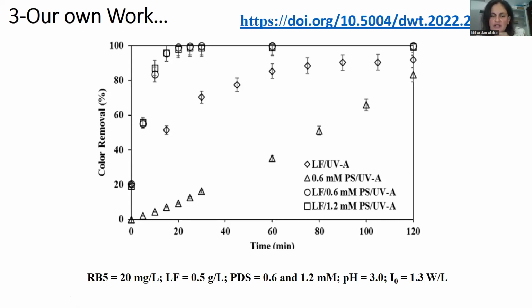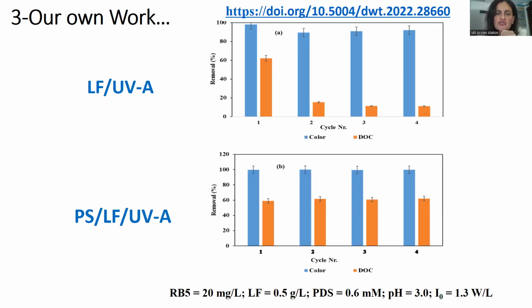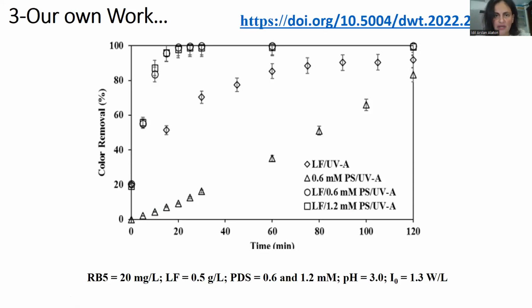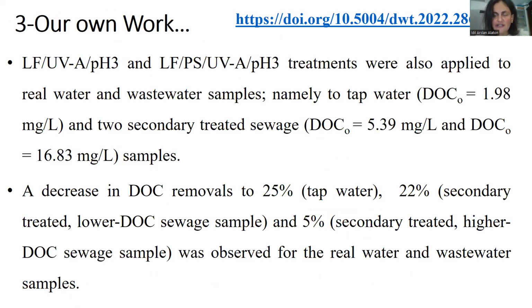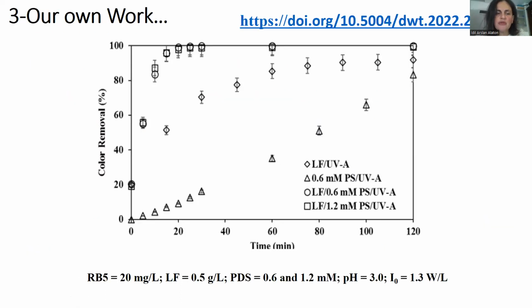Here we have optimized conditions. So interesting here is, or promising, let me say that, well, we have to work at pH 3. This is not so attractive, by the way, and we need strictly acidic pH. If you go up to 4 or 5, we have problems. So we have the slowing down of reaction rates.